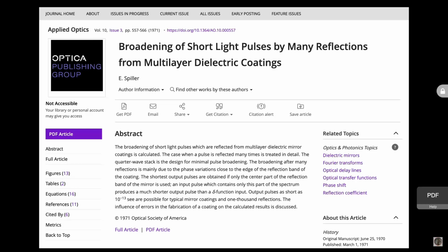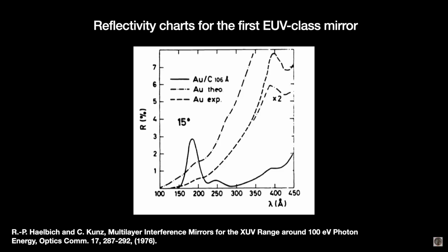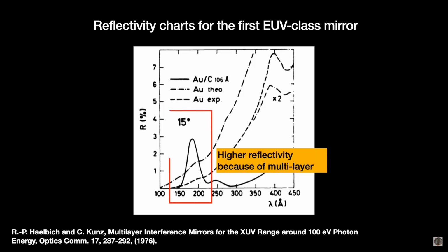validate his theory. Two years later, IBM collaborated with the Germans to fabricate these special multi-layer mirrors for tools like X-ray telescopes. After some interruptions, in 1976 they produced a 9-layer mirror of carbon and gold. Its reflectivity of 20 nanometer wavelength EUV light was measured at about 3%.